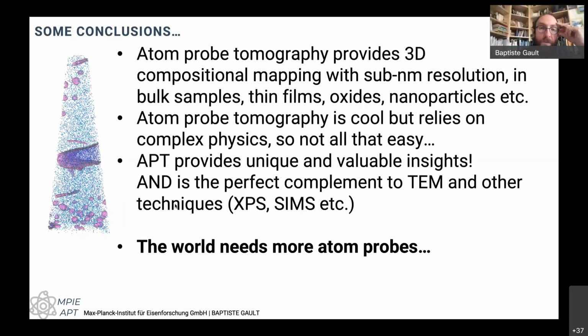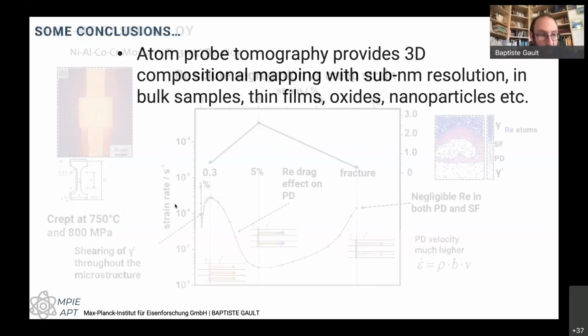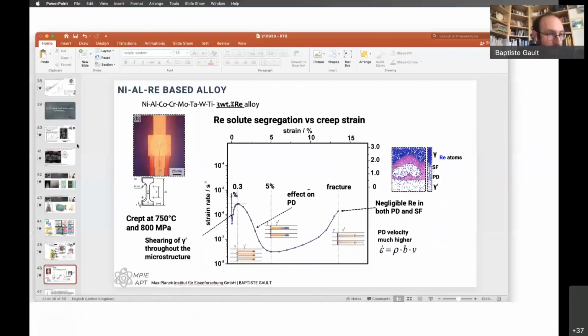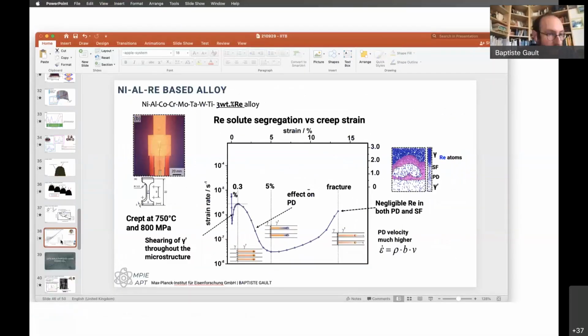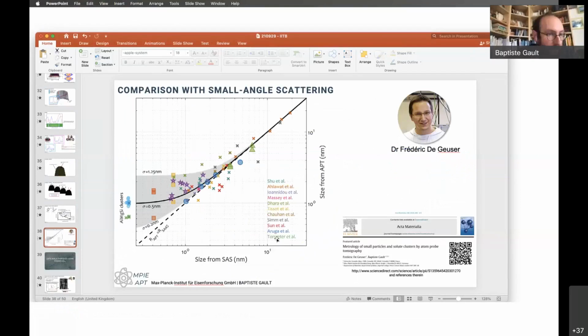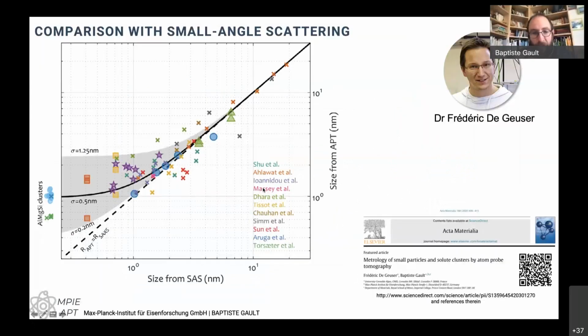So what is the smallest object that we can look at confidently? It really depends a bit. So maybe I should get back to that graph. Here we didn't say which alloy it was because ultimately it doesn't matter that much. But here you'll find some aluminum alloys, some steels, some ODS oxide particles in steel. It's very varied, but the limit in resolution seems to be somewhere around a nanometer or 0.5 nanometer. So it's already hundreds of atoms, right?